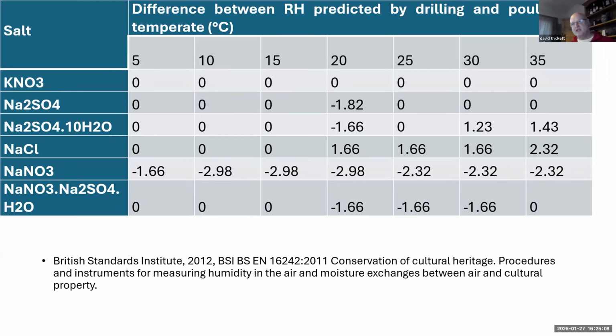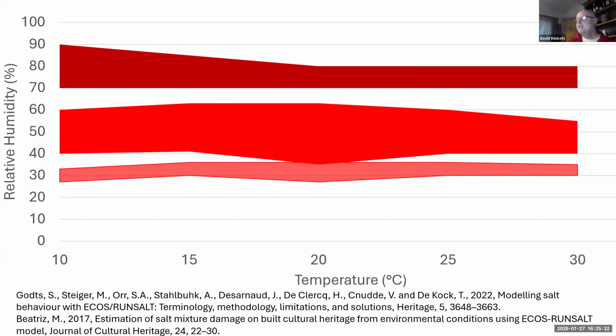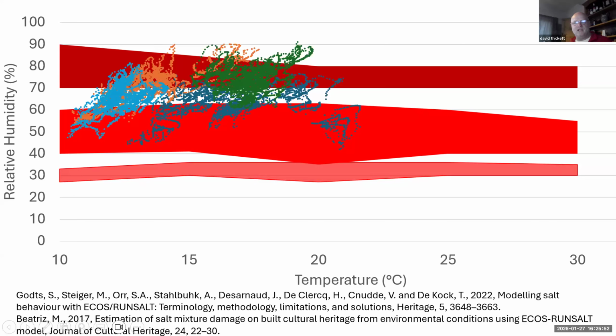And we've compared poulticing with drilling and how it affects those boundaries at different temperatures. And what we found is certainly with a lot of stone, it makes a little bit of difference, but the difference in terms of relative humidity is probably smaller than the error on the instruments we're using in museums to measure it. So we can probably just ignore that difference and go ahead with the poulticing. And then another example, much worse example, this is Furness. This is the salt from that Abbott's Head that you saw. And we have very few white regions, and the darker the red, the worse it gets. And if we put the temperature and relative humidity over, you can see we've got, it's bad, but a lot of it is actually still okay. And we've been able to use that to predict what we're going to do with the environment at Furness.